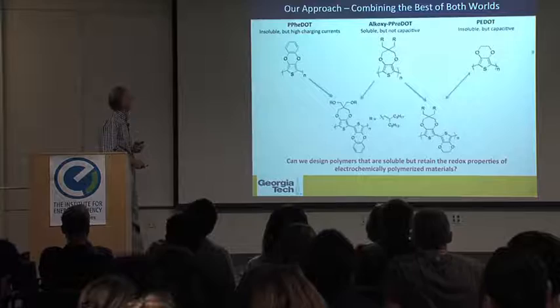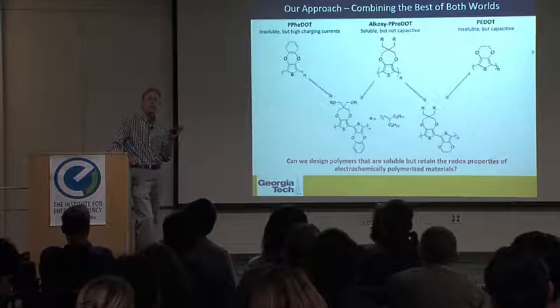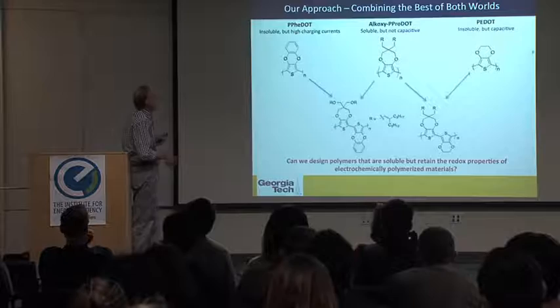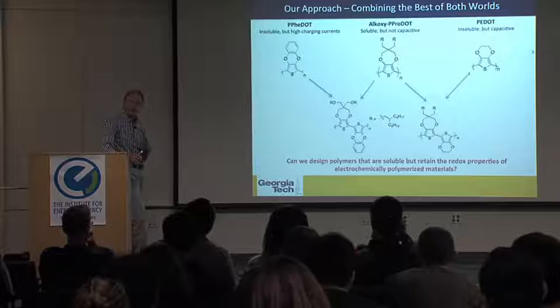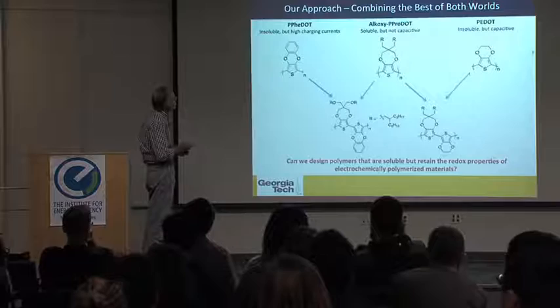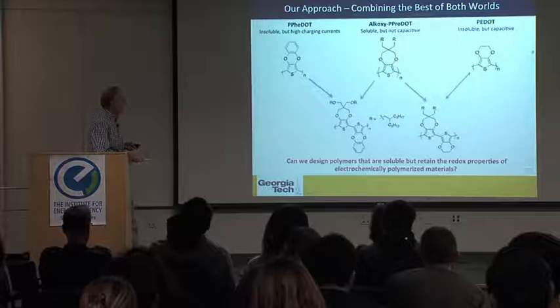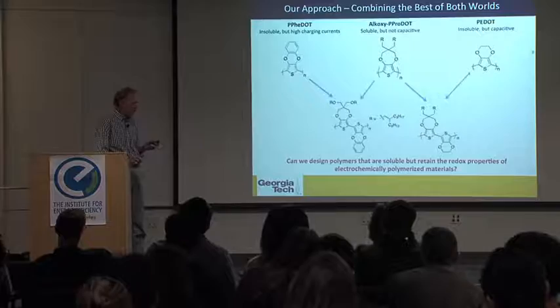Okay. Well, electrochemical polymerization is not going to go anywhere. We need to be able to solution process these materials. But what we do know is that if we have these types of polymers, such as these propylene dioxythiophenes or ethylene dioxythiophenes that we all know as EDOT, they are very electrochemically active, very capacitive, but totally insoluble polymers. By placing substituents on here for solubilization, we have a very high level of electroactivity, but we lose a lot of the capacitive nature. So the question we asked, a very simple question, is can we design polymers that are soluble but retain those redox properties of those electrochemically polymerized materials?